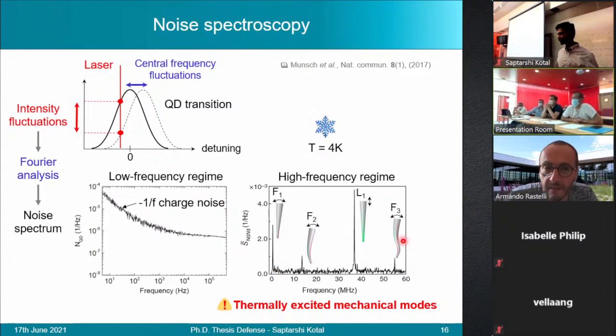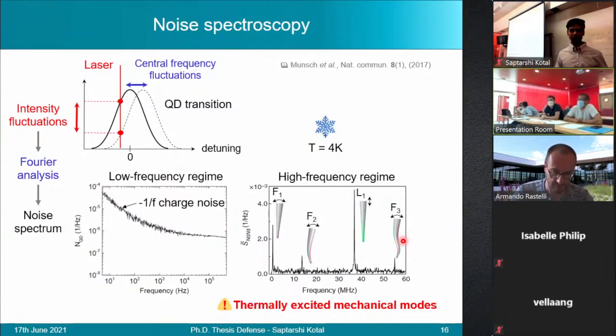So they had two detectors where they tuned the laser off the resonance, and then they were measuring the emitted photons split on a beam splitter, and they were measuring the correlation time across two detectors. And then by doing a Fourier transform on the measured correlation signal, they obtained the following peaks.